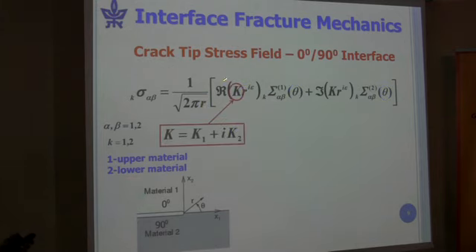Okay, now K, we're used to K1 Roman and K2 Roman, and here we have this K1 and K2. This is for interface cracks, the mode 1 and mode 2 stress intensity factors, which are combined into a complex stress intensity factor. And so if we look at the units of K, this, by the way, is the real part of this. This is the imaginary part of this. So everything is real, the stresses are real, not to worry.